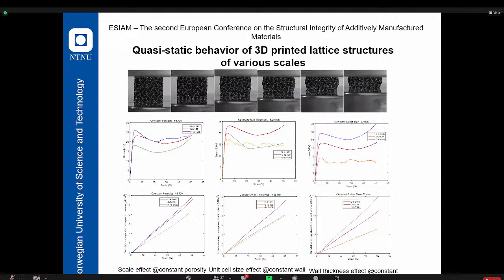For the second category, it's the wall thickness effect at constant cube size. So all the lattices have the constant cubic size, but the wall thickness varies, and also the unit cell and the porosity. And the last one is the unit cell size effect at constant wall thickness. In this case, the wall thickness of all the sheet-based lattices is constant, but the unit cell size, cubic size, and the porosity vary.